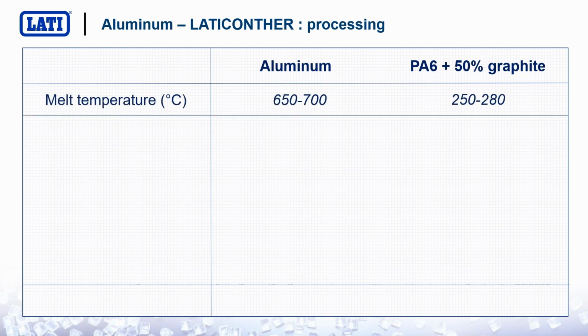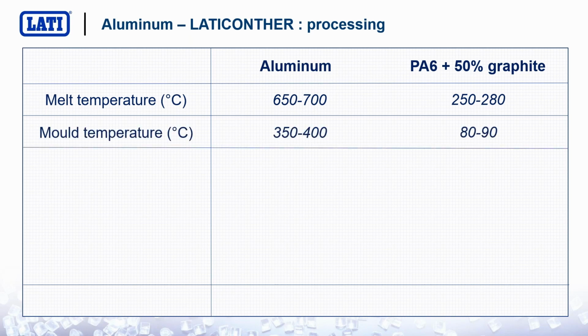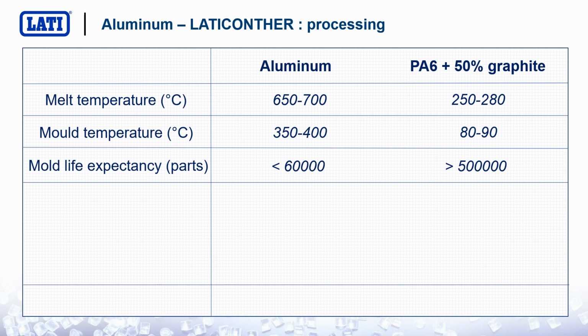Let's talk about the processing. When it comes to processing, you also pay the electric bill, let me say, and you also have to pay the maintenance of your equipment. When it comes to processing, the difference is really outstanding. The melt temperature aluminum versus graphite is 700 degrees versus 250. The mold temperature is very different as well. The mold life expectancy is extremely different.